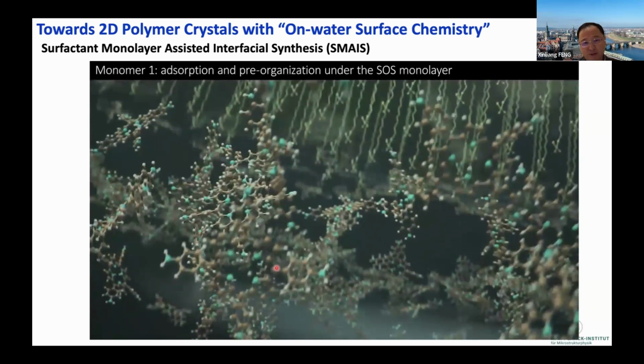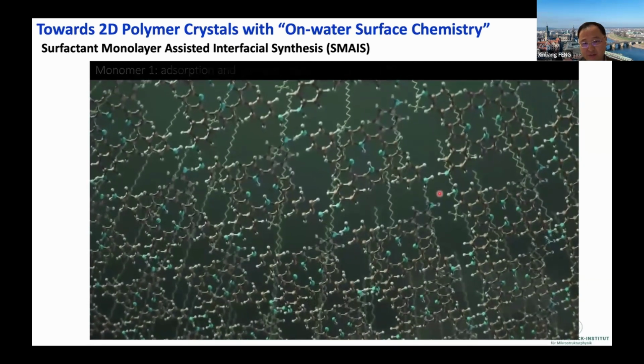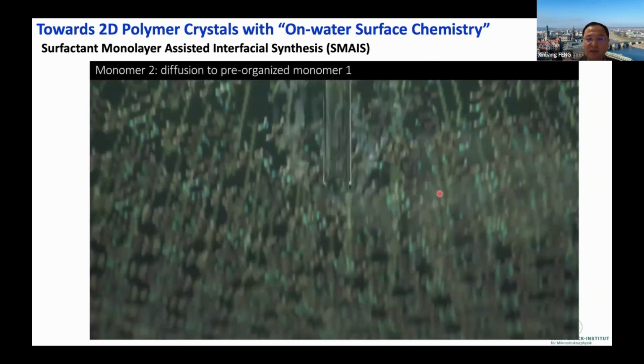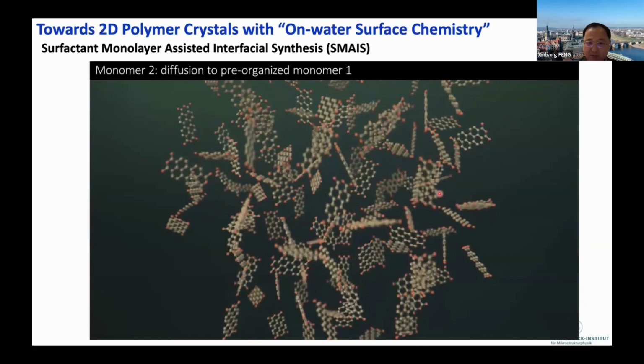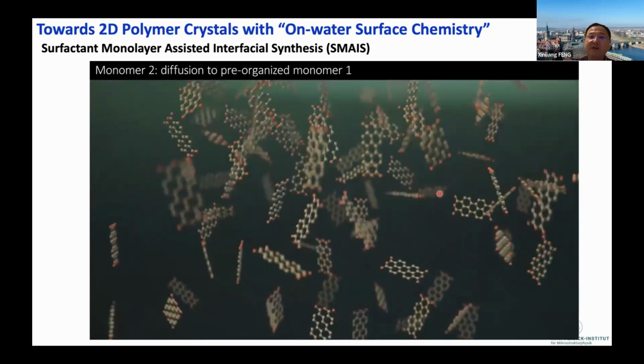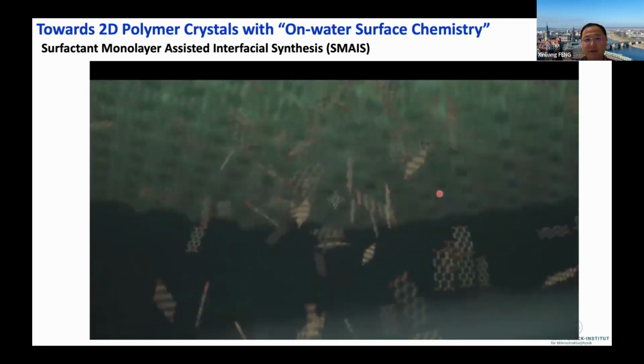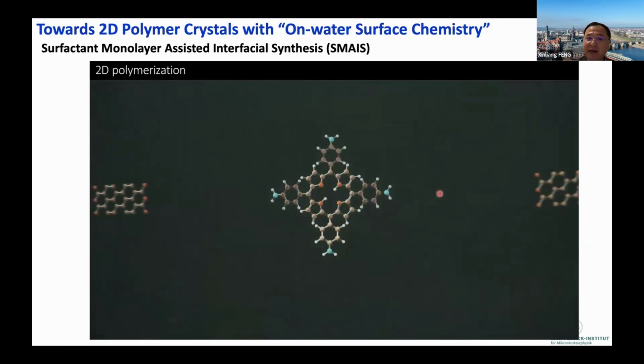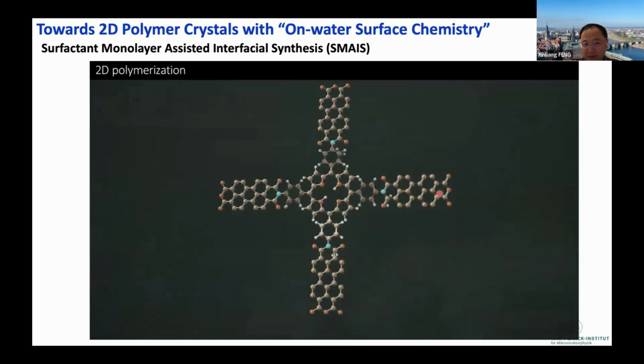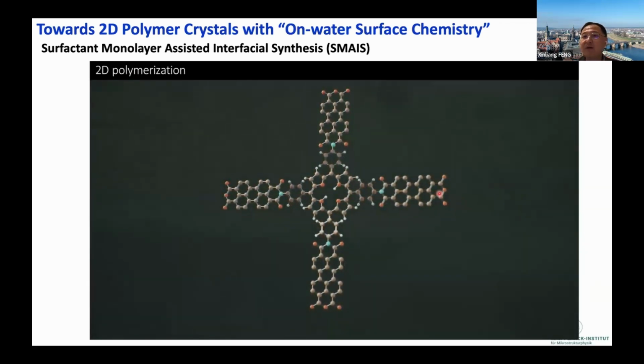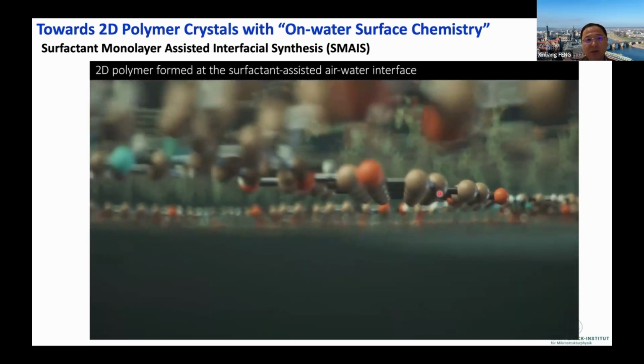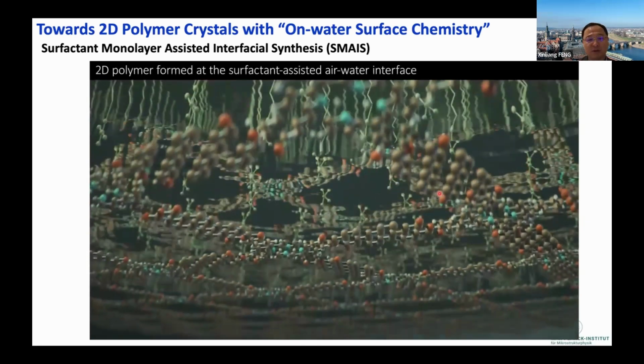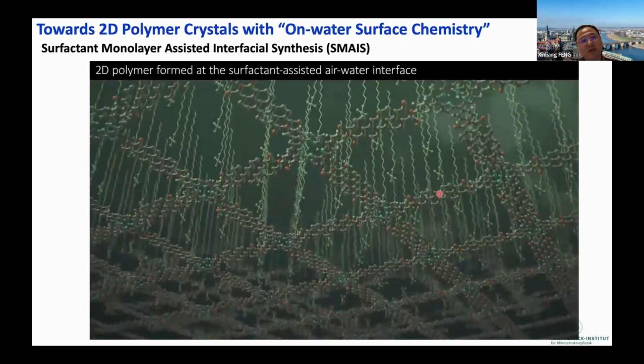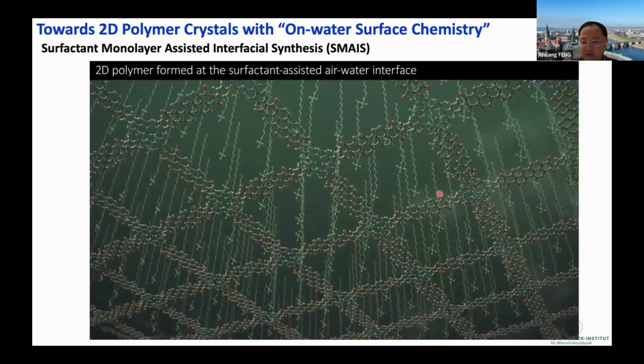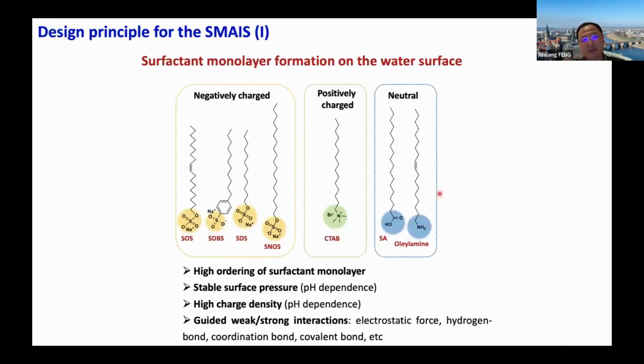They will diffuse to the water surface by pre-organization in a very good arrangement. Then we add the second monomer into the water solution, which further diffuses to the water surface. And on this water surface, at the air-water interface, okay, the molecules can polymerize with very good reactivity. And they lead to the two-dimensional arrangement with a highly porous structure, which ends up as the so-called polymer monolayer or organic framework materials.